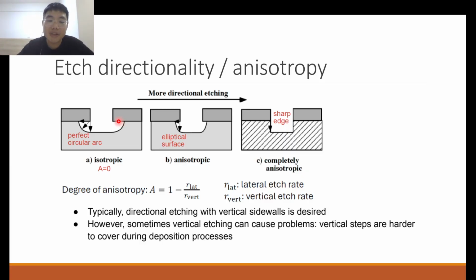So we can have a factor that quantifies this directionality or anisotropy, called the degree of anisotropy. You just take your lateral etch rate, which is the etching in the left and right directions, over your vertical etch rate, and you take one minus that ratio. So if let's say you do not etch to the left or to the right at all, this numerator is 0 and your degree of anisotropy is 1. It's perfectly anisotropic. The anisotropy degree is unity.